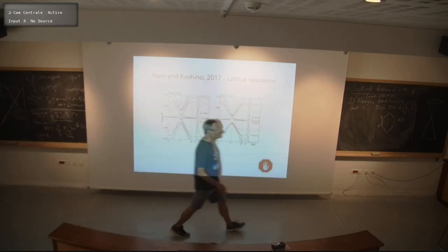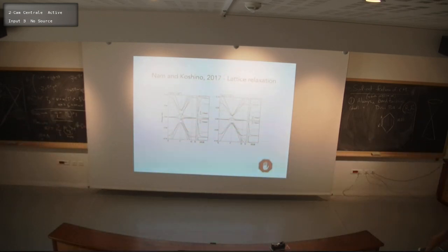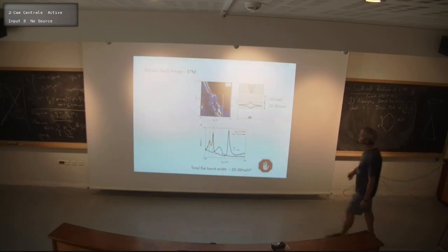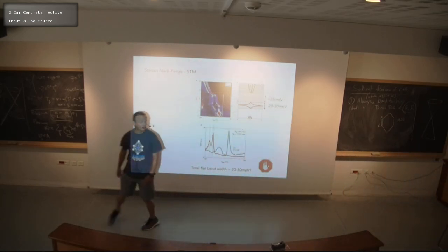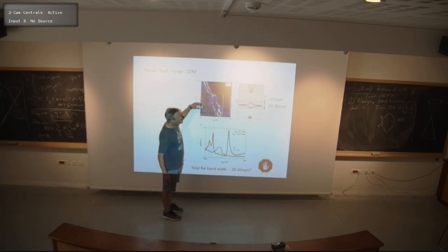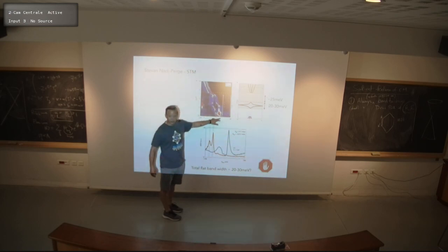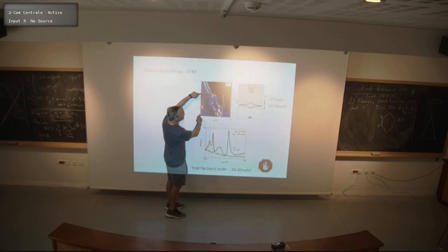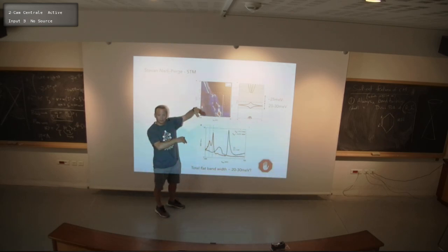All right. So that's theory, right? Here's some experiment. Okay. This is a very recent experiment. We'll come back to it later. It'll be important later. But this is STM from a group at Caltech. This is a plot of differential tunneling conductance from an STM into twisted bilayer graphene. This is the bias voltage, so the voltage between the tip and the sample, and this is a backgate voltage, again varying density. So to map it out for you, in this region, the Fermi level is inside the flat bands, but they can go above.